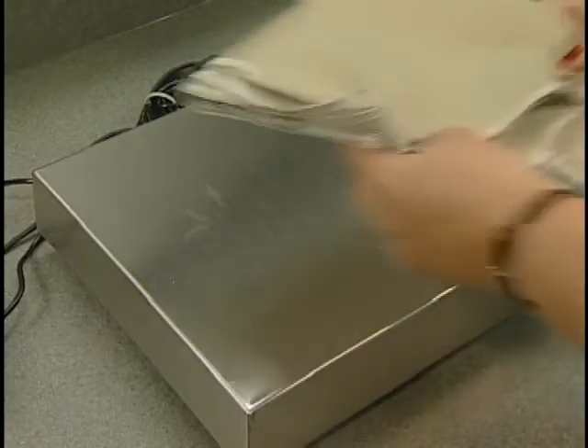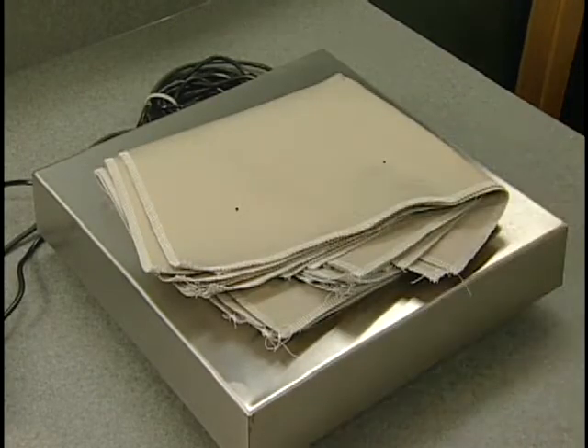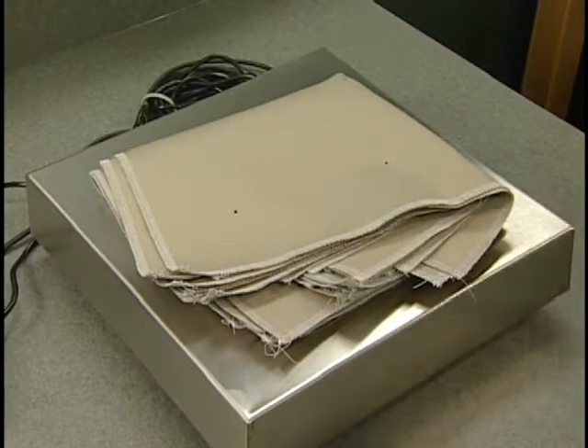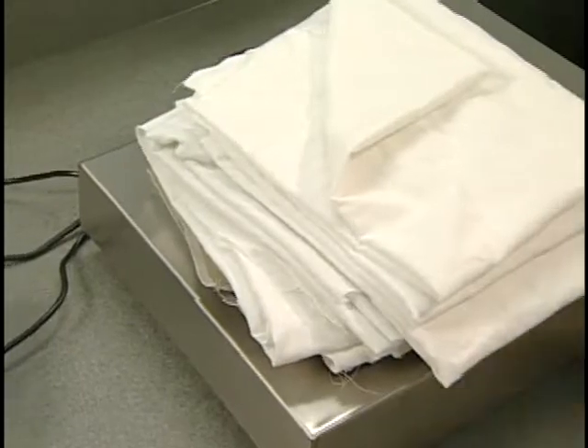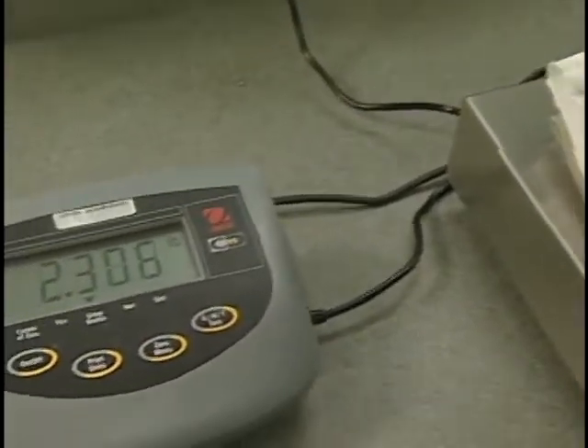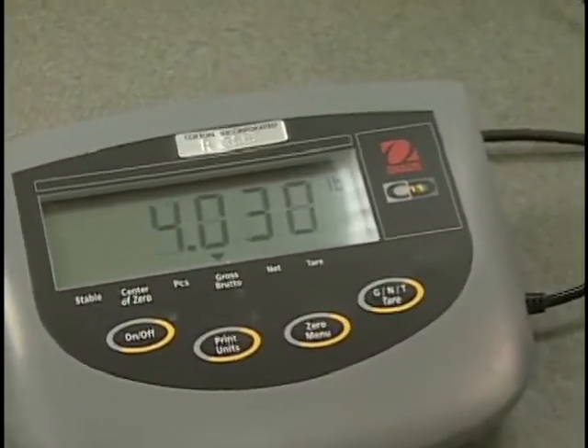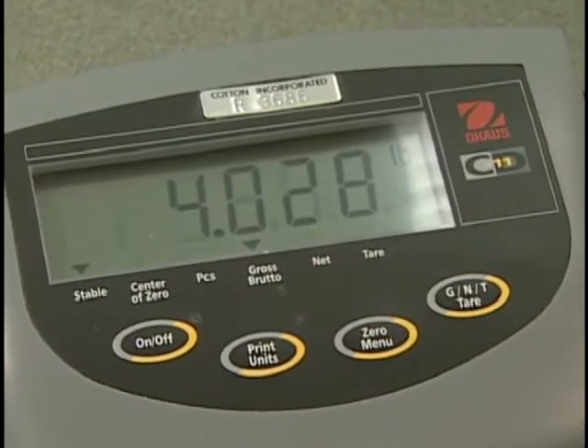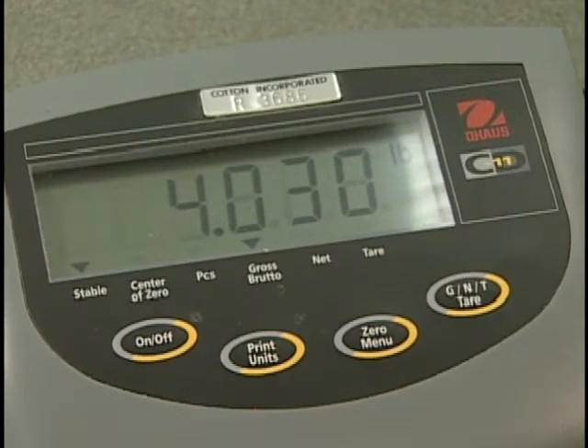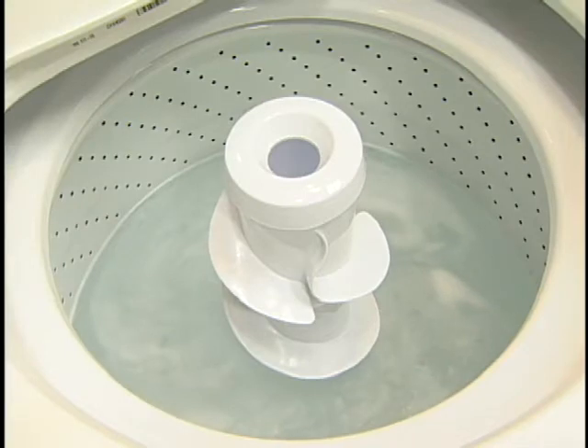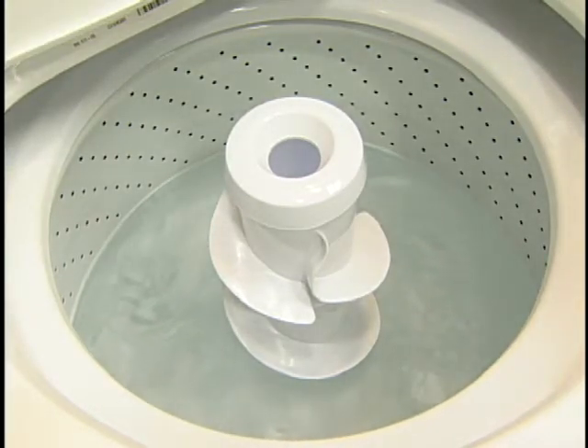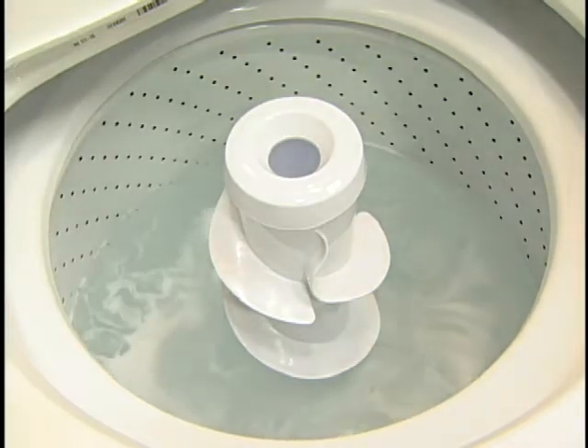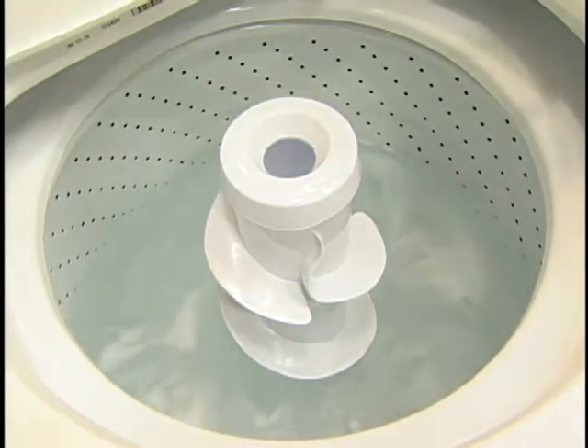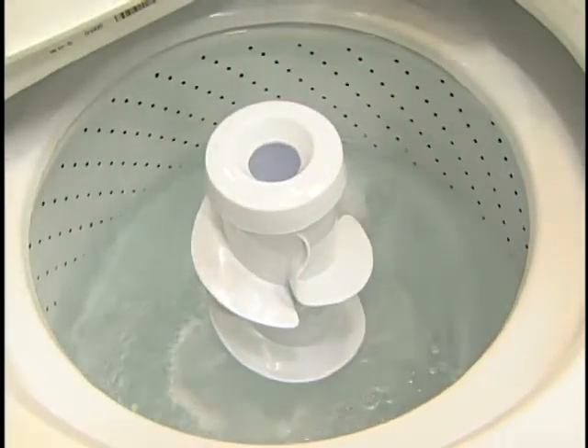The prepared specimens are washed to the standard in a load size of 4 pounds, 1.8 kilograms, including any ballast needed. Sets of 3 specimens are weighed along with the ballast. Ballast for the wash loads is clearly specified as to size and fabric type. The washer is filled with 18 gallons of water at the specified temperature. The water temperature can be measured by hand or controlled by the use of a microprocessor control that automatically blends the hot and cold water to the desired temperature.